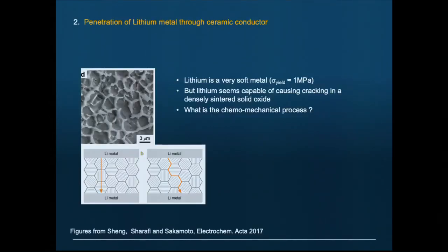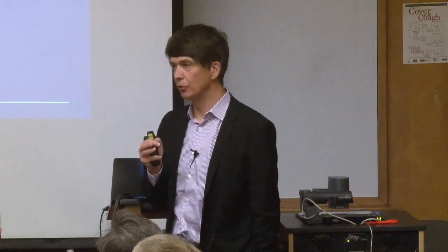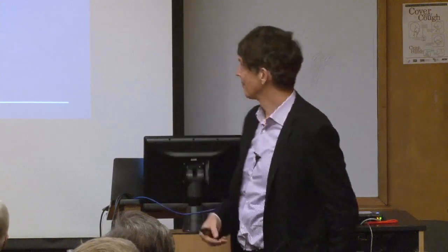The other one is, to make this worth our while, we also want to go to a lithium metal anode, right? Today we use graphite, but if we can go to lithium metal... We don't use lithium metal today in liquid ion batteries for safety, because lithium tends to easily form dendrites when it's plated, and it just makes a dendrite and it short circuits to the other electrode. People have this belief that in solids, because solids are hard, lithium is a really soft metal. The yield strength of lithium is like 0.7 megapascal. It's a little above butter, right? And so people believe that if you put a hard solid in between the electrodes, lithium will not get through it, and so you won't have shorting. Well, that's what we thought.